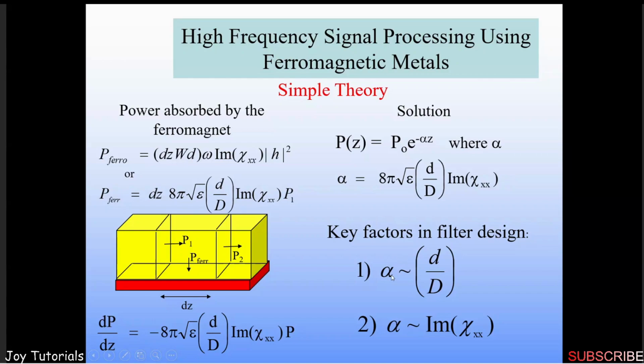There is absorption of this material, how much energy is absorbed. This depends upon the thickness of the magnetic layer, the red one here. It also depends upon the thickness of the dielectric layer, but we have to do some adjustment not to make too much eddy current losses, because the magnetic material is a metal. We can also use an insulator like yttrium iron garnet, but it is not a very good material for going towards the high frequency range. It has a very low saturation magnetization. So we use the iron film, but iron film has an eddy current loss, so we cannot go beyond a few tens of nanometers or 100 nanometers.